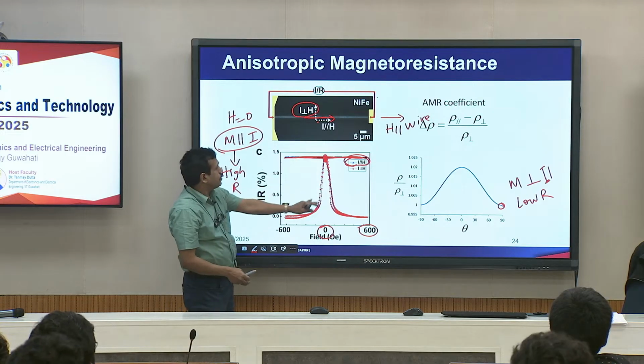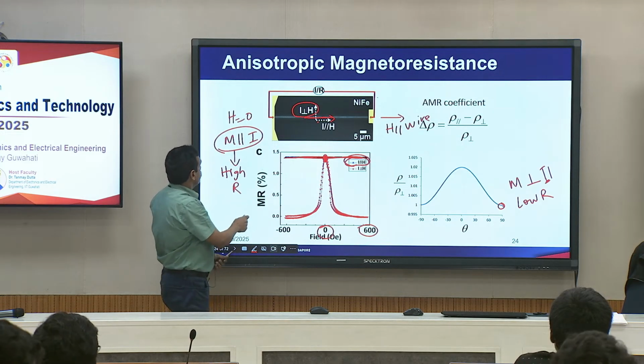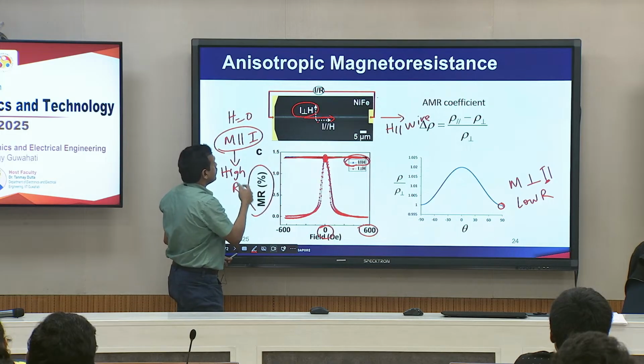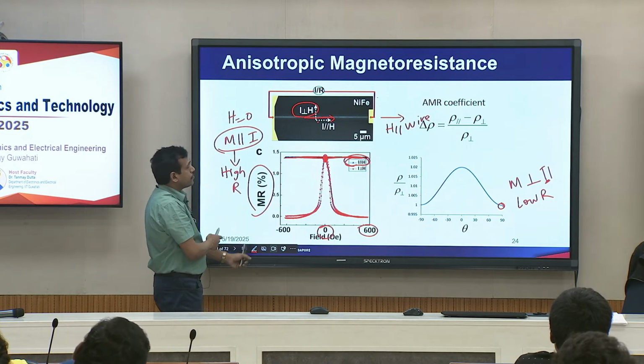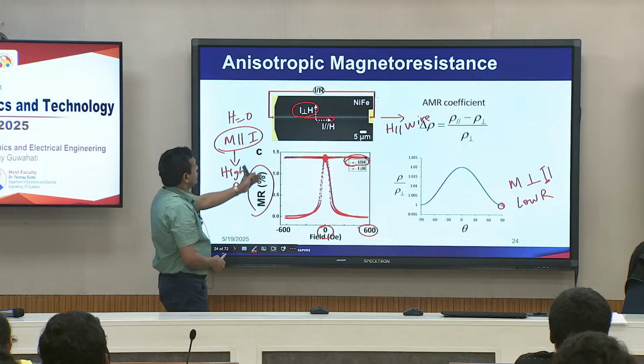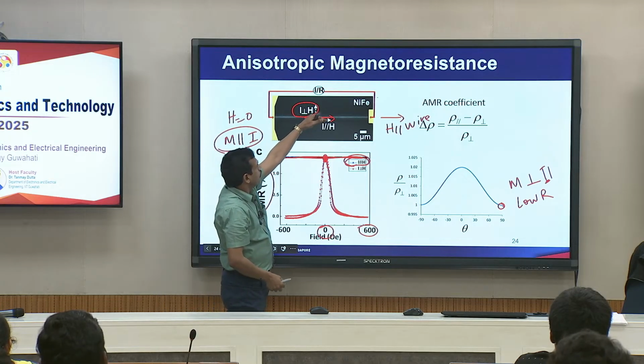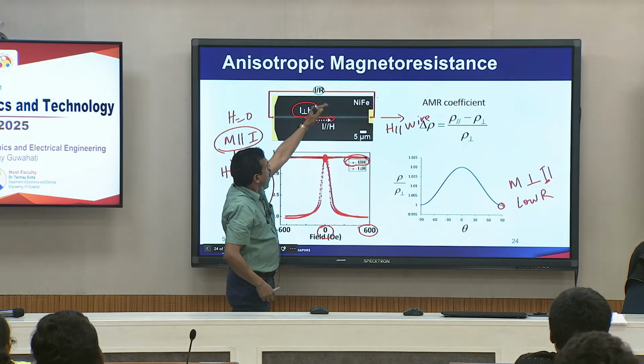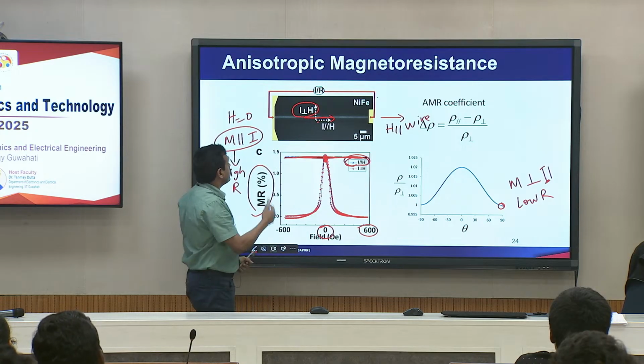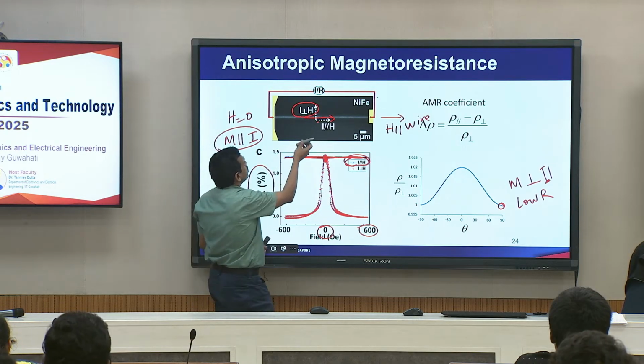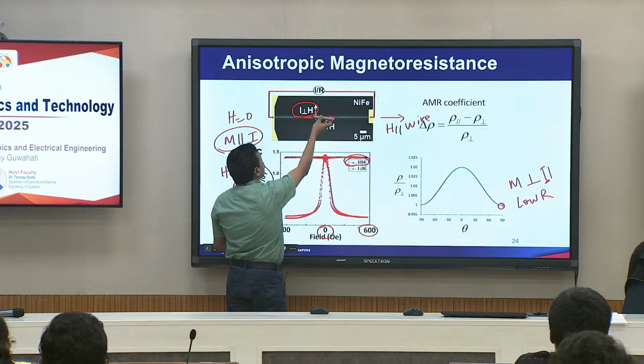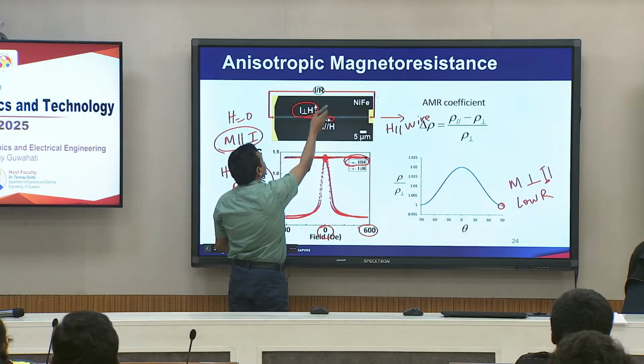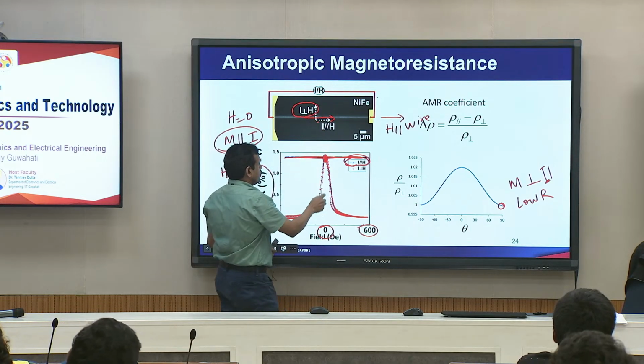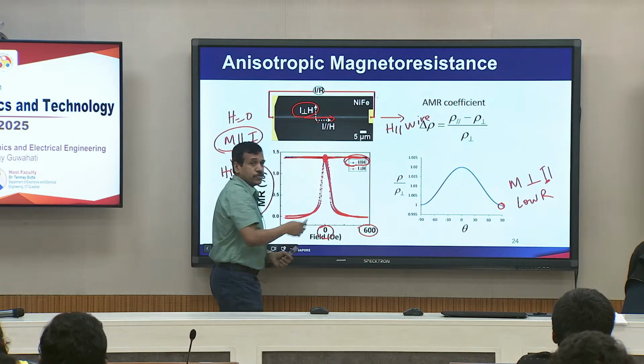Okay, so this is what happens when you try to measure the magnetoresistance of a material as a function of magnetic field. You can change the magnetization to be either parallel to the current or perpendicular to the current. So, in this case the magnetic field changes the magnetization direction from easy direction to the hard direction and so on. So, we see changes in the resistance.